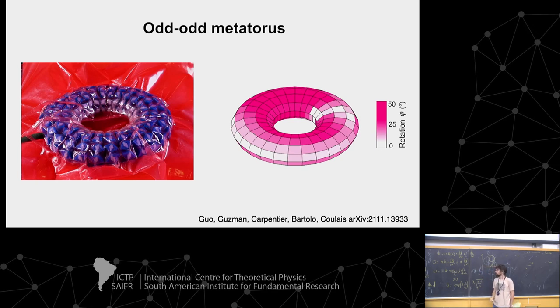And so now, instead of this linear PDE that admits exponential solutions, you have an equation that is so-called, this is really a phi to the fourth equation. And from the literature, you know that this phi to the fourth admits solutions of the form hyperbolic tangent of (x minus x0) over lambda, where lambda is your characteristic length scale.